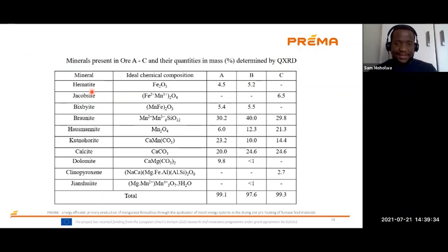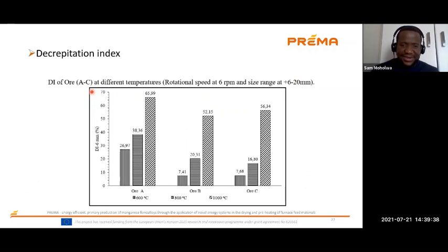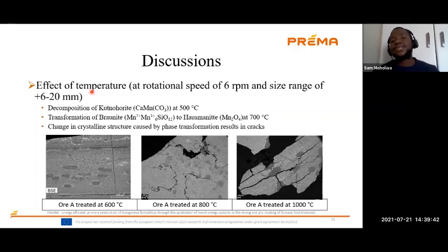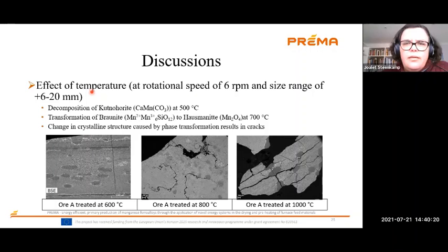Okay, from the results we got from the SEM, we didn't really notice much porosity per se, but what was obvious was the presence of cracks in these samples. When the samples were taken through the kiln, you can see that with temperature we had many more cracks. But in terms of the ore, I don't think it became more porous after being taken through the kiln, it just had more cracks than the initial sample. Yeah, the intention was not to have reduction reactions, so it makes it a bit different from sponge iron production.